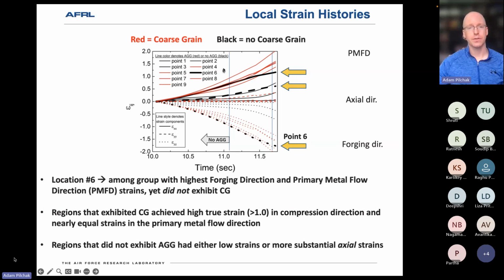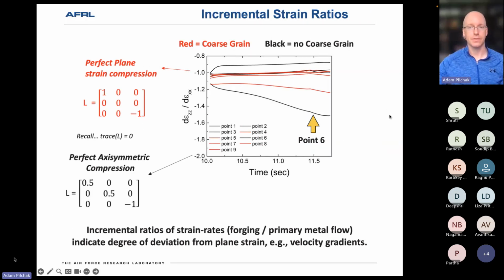From here, we were also able to determine that locations that didn't see a strain of around 1 or so never formed abnormal grain growth. So there seemed to be a critical strain threshold. But then there also seemed to be a critical strain path threshold. I'll go to the next chart because I think it's easier to see this.